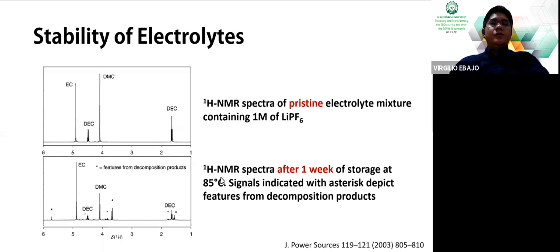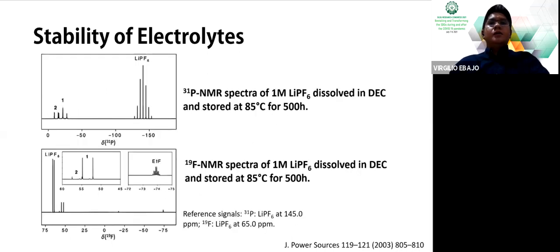Now, after 1 week of storage of the solution, the electrolyte solution containing the mixture of organic solvents and the lithium hexafluorophosphate, the proton NMR shows that there are new signals that are not coming from the pristine solvents. So this means that during storage at 85 degrees for 1 week, the organic solvents decompose, resulting in the generation of new signals in the NMR spectrum.